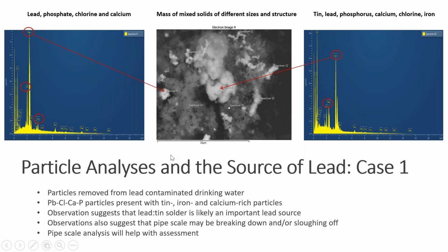So when I look at this kind of thing, I think to myself, okay, it's a mix of stuff that's just bound together. What could be going on here? And so I think this suggests that you've got an area within this pipe, and they do have a lot of lead tin solder. Within this sample, a 1 liter sample, you're certainly hitting those lead tin solder joints. And so this likely suggests that you've got some sloughing off from a region around or near a lead tin solder joint, because you're seeing the tin, you're seeing the lead, and you're also seeing some other things.